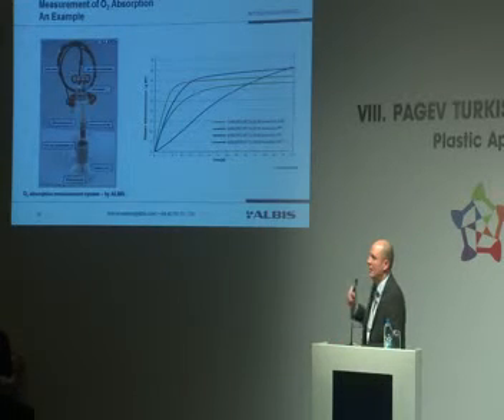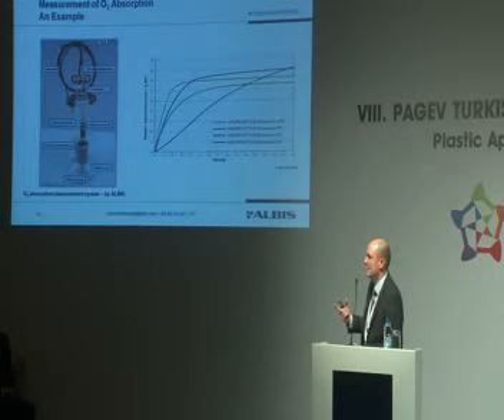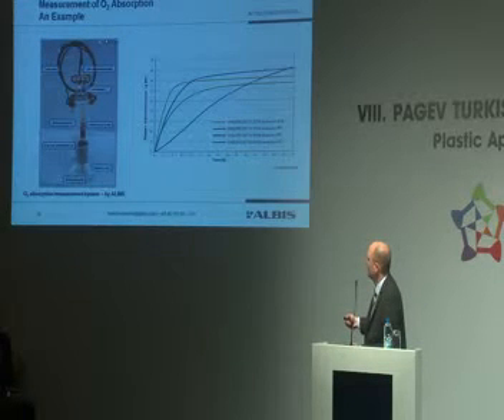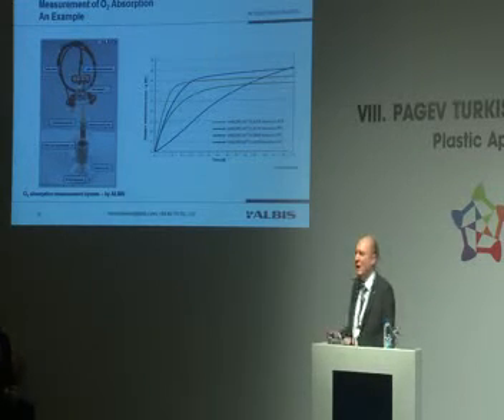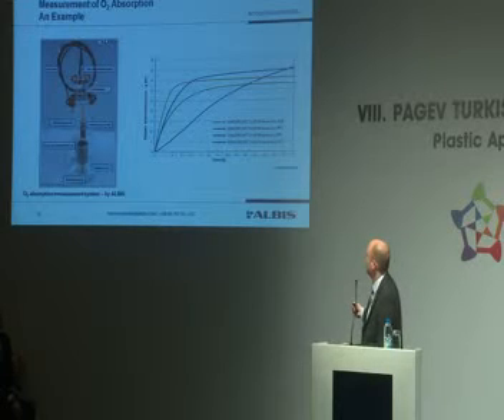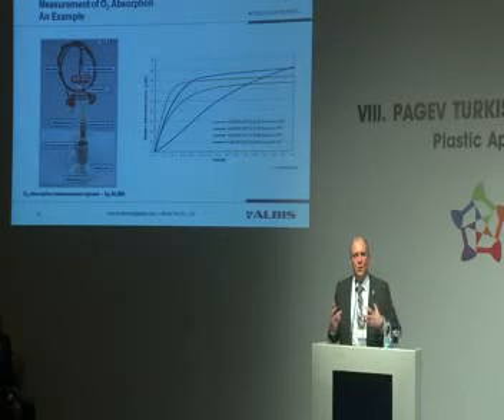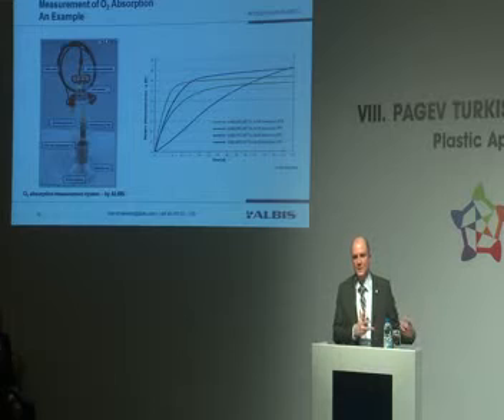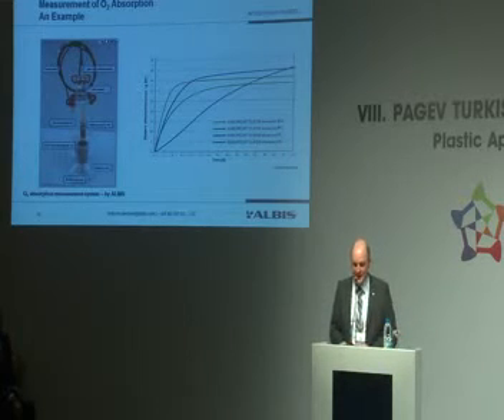So what I've said before, oxygen scavenging, which time frame does it take? As you can see here under these conditions, so 100% humidity and 21% oxygen concentration inside this vessel, we reach a plateau after 8 days. So for 8 days, we see a really huge oxygen uptake. And after those 8 days, we reach the plateau. So the capacity is used. All of the iron that was inside the film has turned into iron oxide.